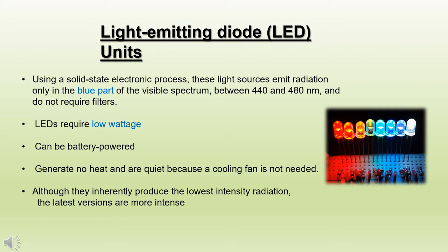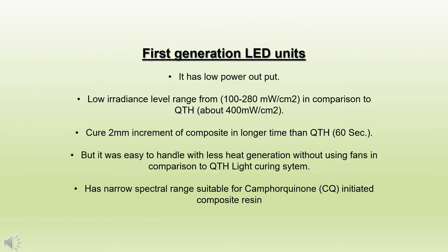They do not require filters because they emit light at specific wavelengths within the 400 to 500 nanometer range. And over time, only little degradation of the light output is observed. The first blue LED curing lights were experimental prototype models built to test the concept that they could generate light at the correct wavelength and deliver sufficient number of photons needed to successfully photocure dental resin-based materials. It has low power output, it has low irradiance level ranging from 100 to 280 milliwatt per centimeter squared in comparison to QTH, which is about 400 milliwatt per centimeter squared.